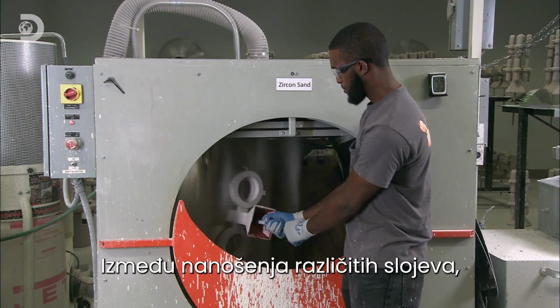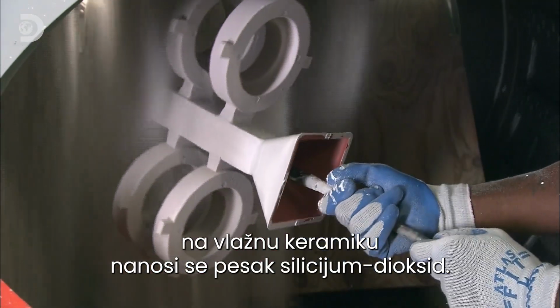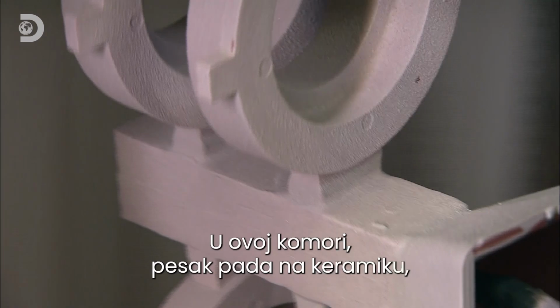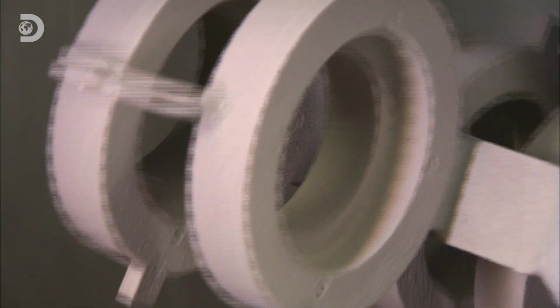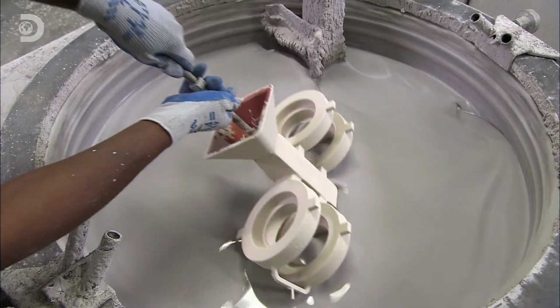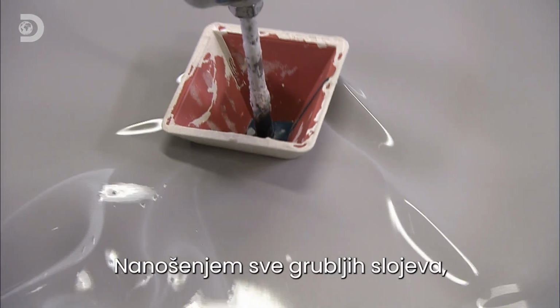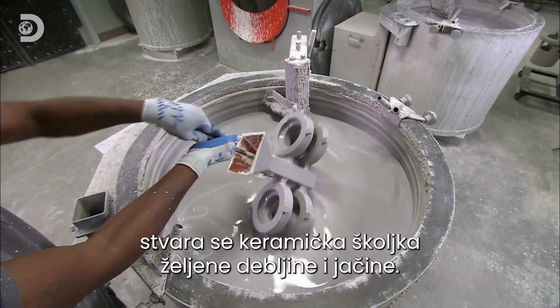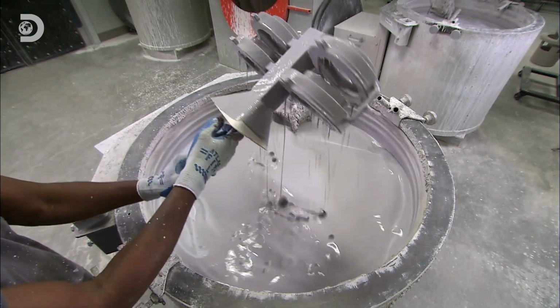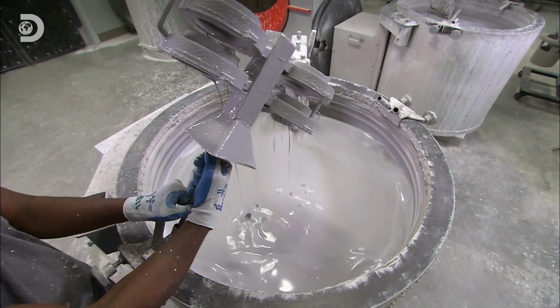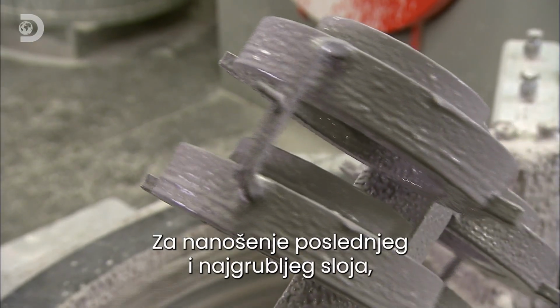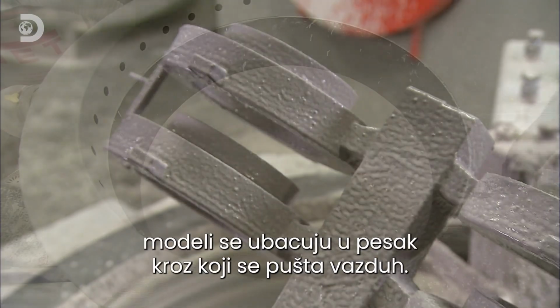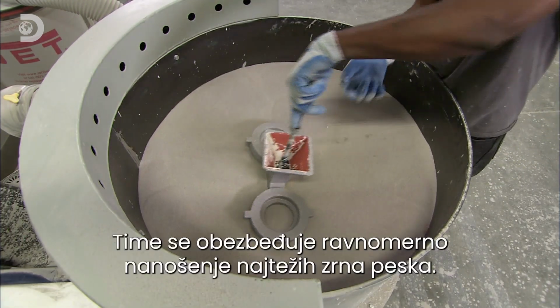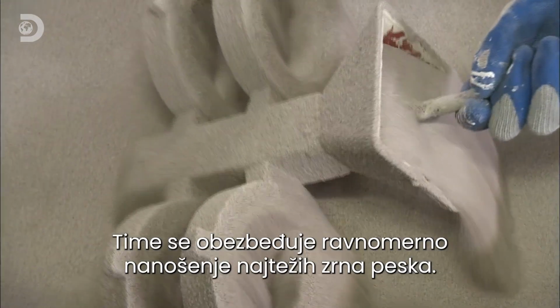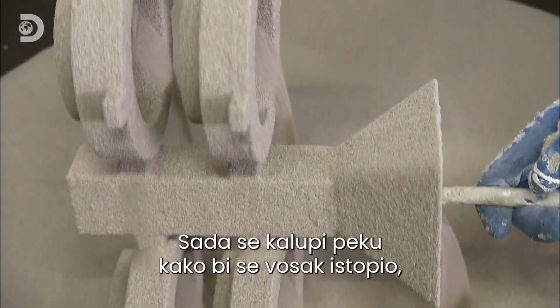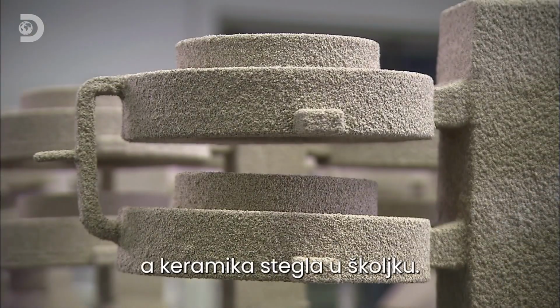Between coatings, silica sand is applied to the wet ceramic. In this chamber, the sand rains down onto the ceramic, creating a stucco effect. By building up layers that are progressively more coarse, a ceramic shell with the desired thickness and strength is created. To apply the final coarsest layer of sand, air is pumped through it as the models are dunked into it. This ensures a uniform coverage of the heavier sand. The forms are now baked to melt the wax and harden the ceramic, creating a shell.